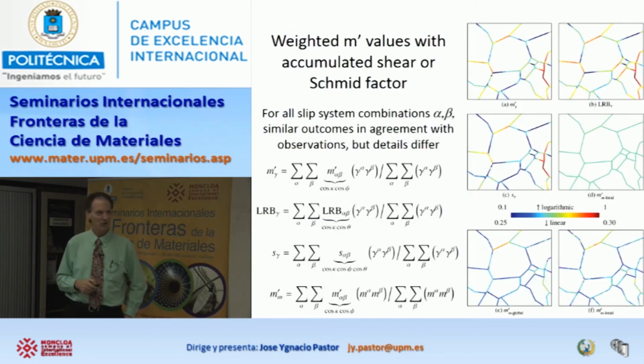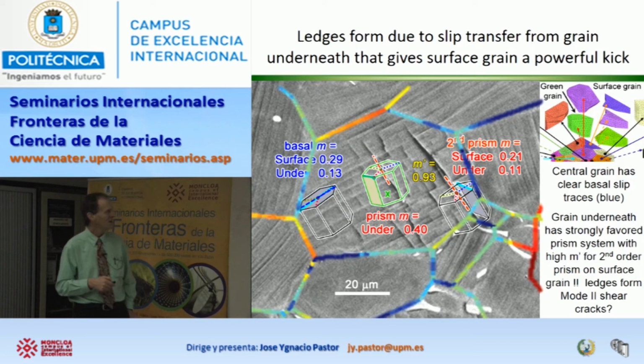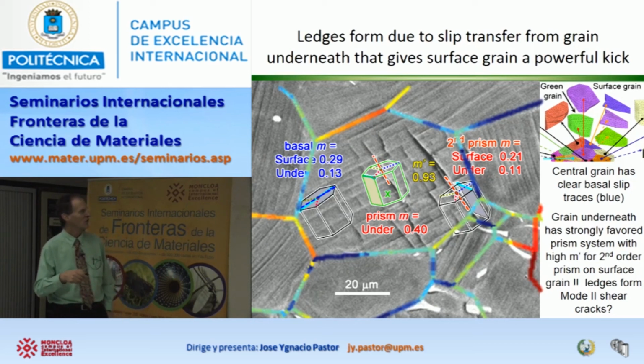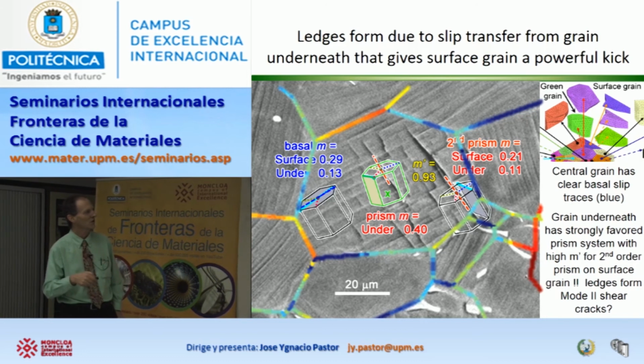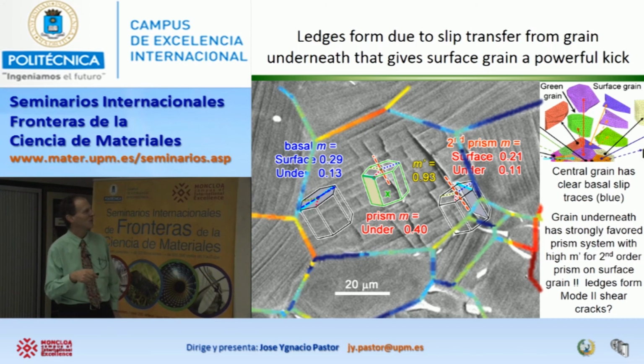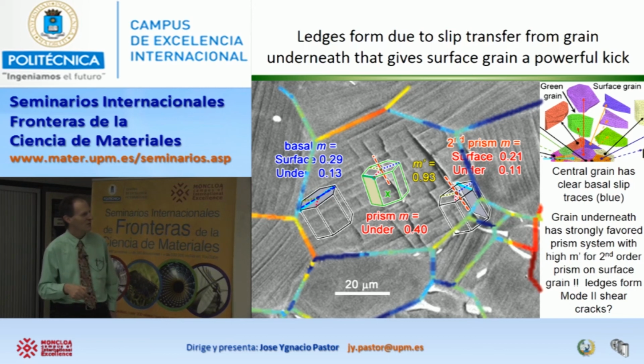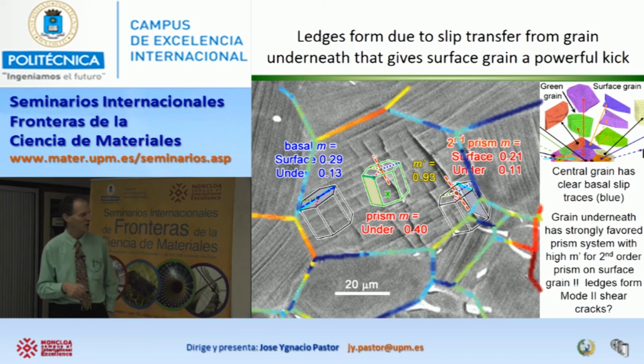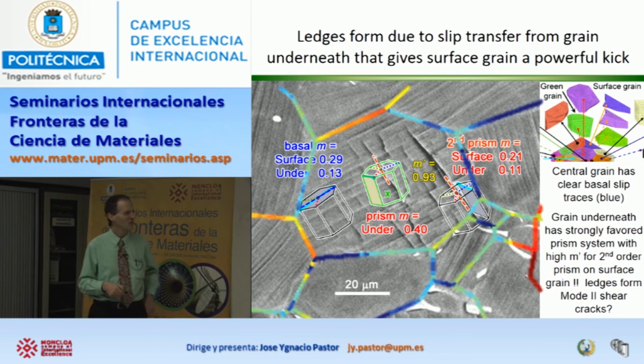And once we have a 3D microstructure, we can evaluate several of these different kinds of parameters for what the value is along the grain boundary. And I'll give you a sense of that here. So I mentioned to you before that we have good slip transfer going across this boundary. And here, too, we have a parameter that says we should. The blue color indicates that. Here too, well, I guess I have this backwards. This is the exception. This says we shouldn't get slip transfer, but we do get slip transfer on the ones that are yellow and orange. And over here, there are grain boundaries, but there's such good slip transfer across these grain boundaries that you can't even see the grain boundary because it's perfect. There's no evidence of a grain boundary. So it seems to work.